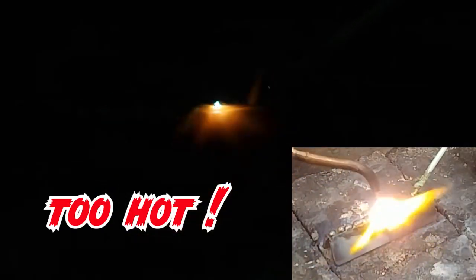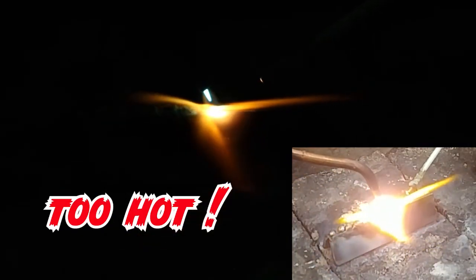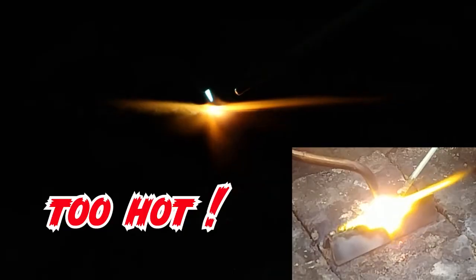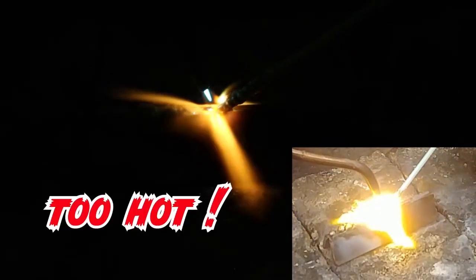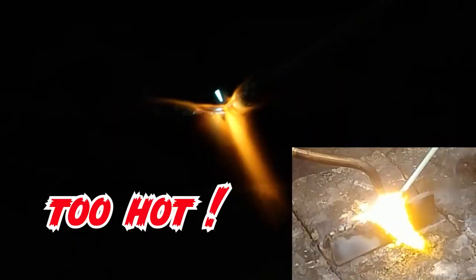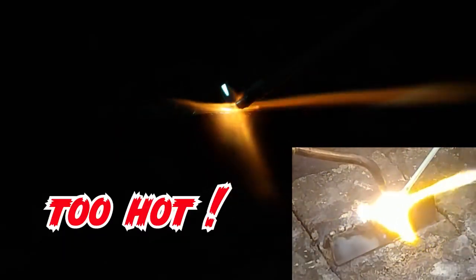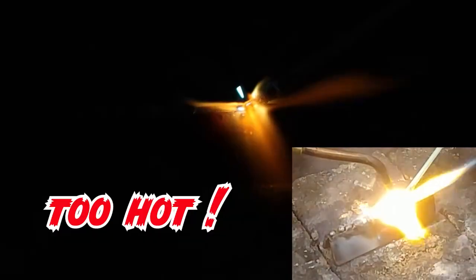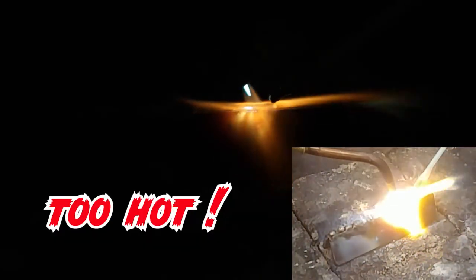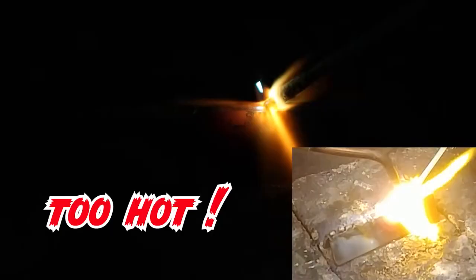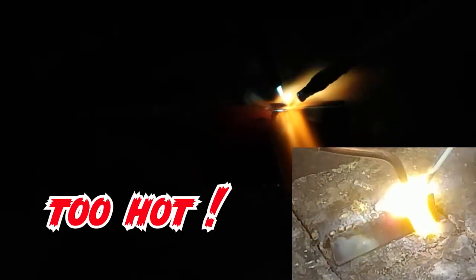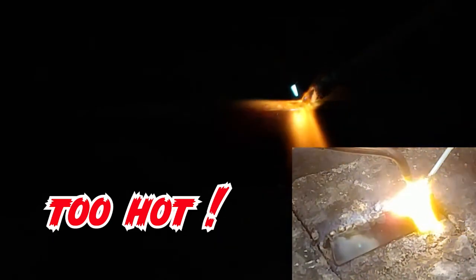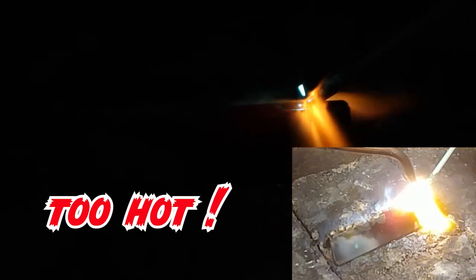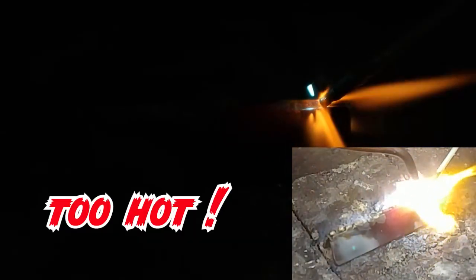So the surface is going liquid already, so this is way too hot for the brazing. And I'm going to not regulate my heat as much. So it's popping like crazy. It's not happy. Should be one good tell. The surface is really runny with brass. It's flowing all over the place. Flux is burning off really quickly too. Lots of good capillary action going on here, but it's probably going all into the inside or down the side.